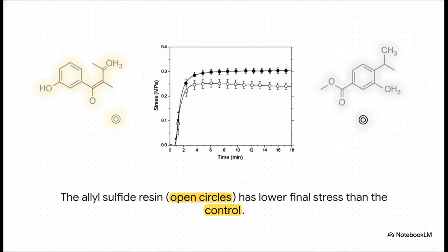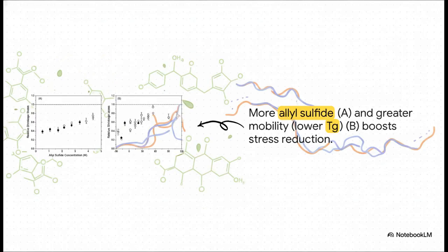But the adaptable network with allyl sulfide develops way less stress to begin with, and you can even see it relax a bit over time. And what's really cool is that you can tune this effect. In graph A, you can see that the more of that allyl sulfide you add, the bigger the drop in stress. Makes sense.